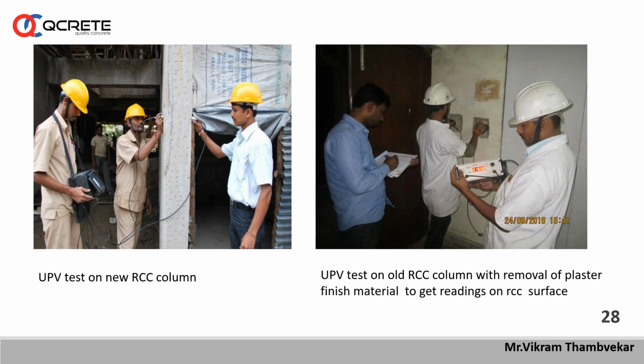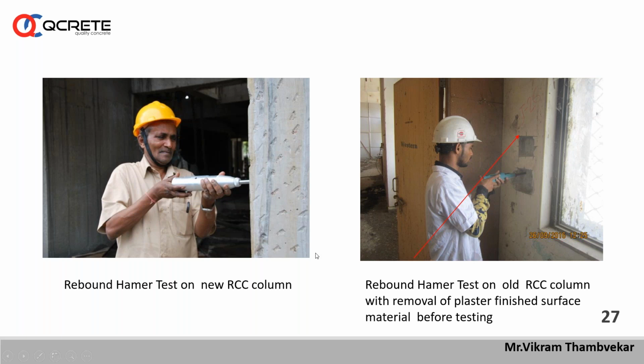So as far as possible, better you check the UPV test in a direct method, and wherever it is not possible to use the direct method, anyone can go with the indirect method. And readings should be taken properly. All these measurements of distance should be measured properly to calculate the UPV values. Secondly, this test is being conducted on all structures, either rebound hammer or UPV.